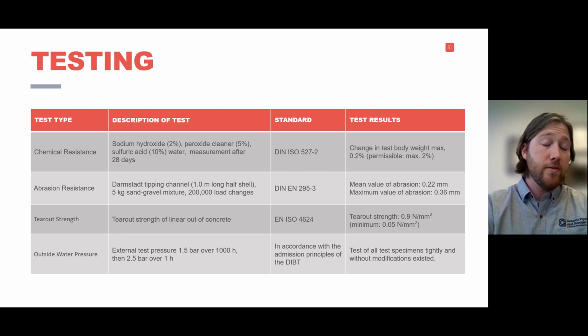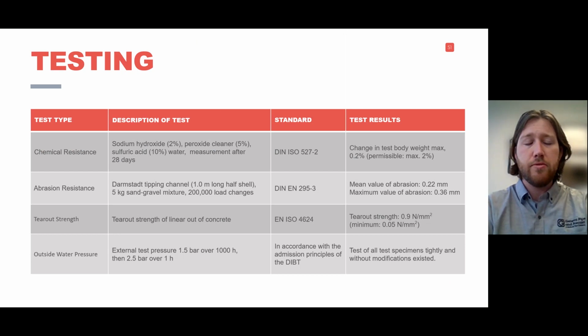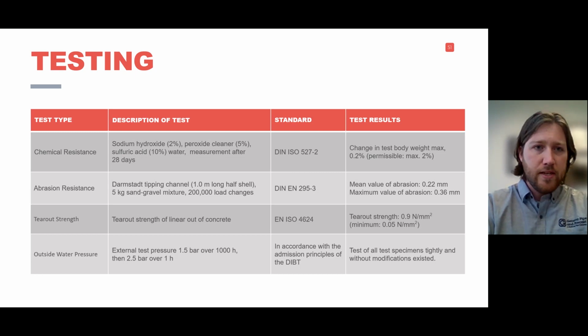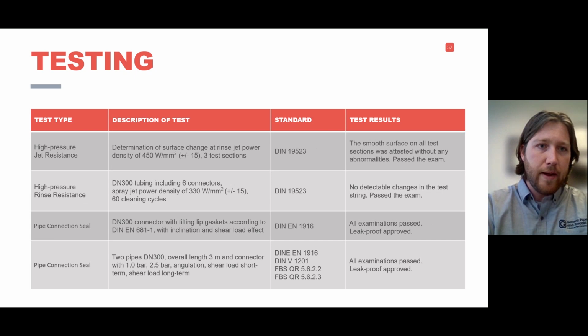Of course, as Elena mentioned, this technology was initially developed over in Europe, so there have been extensive tests done over decades of service. As you can see there, you don't see ASTM on there for the standards, but these different standard organizations are for the European Committee of Standardization, equivalent to our ASTM standards. So they've been tested for chemical resistance, abrasion, tear out strength, outside water pressure. Some more here, high pressure jet resistance for when you go through and want to clean and pressure wash the interior of your system.